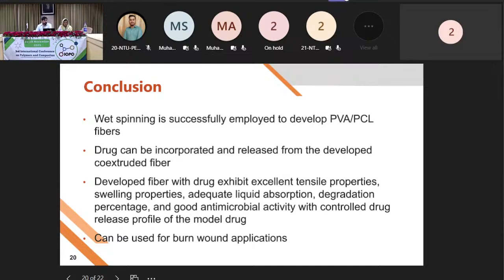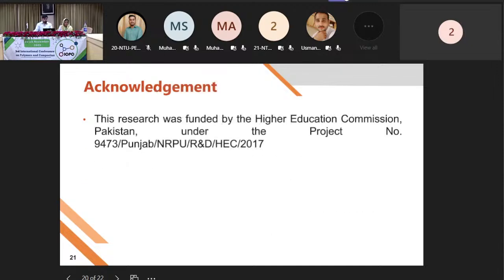PVA/PCL coextruded fibers: the drug can be incorporated into and released from the developed co-extruded fiber. The developed fiber with drug exhibits excellent tensile properties, swelling properties, adequate liquid absorption, degradation percentage, and good antimicrobial activity with controlled drug release. The project number is 9473/Punjab/NRPU/R&D/HEC/2017.